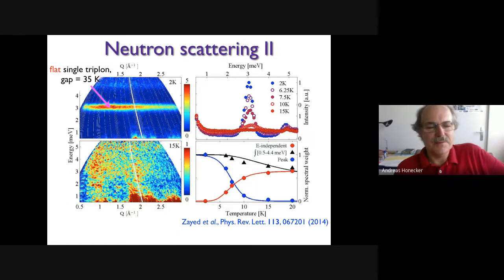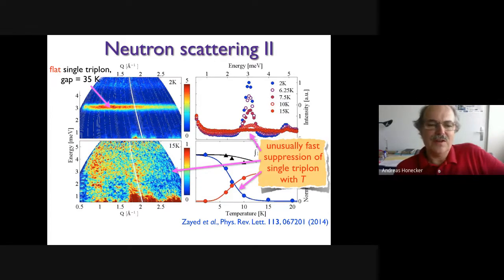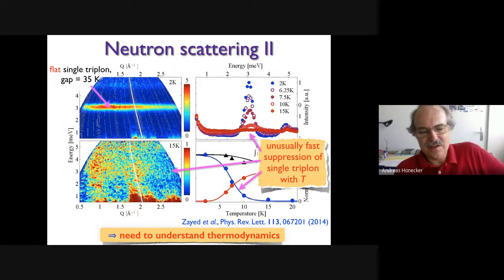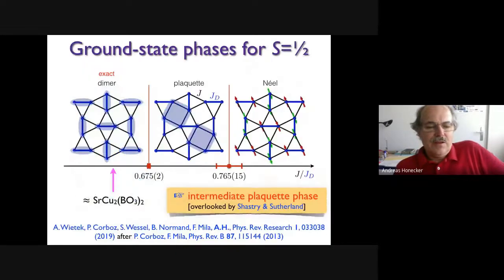Now, what is really striking in the rest of these plots is that if you go to a temperature of 15 Kelvin, which should be significantly below the 35 Kelvin, the dynamic response is completely changed. You see this in the scans, you see this in the intensity integrated plots here. Basically, the temperature scale where things are changing is 10 Kelvin, which is a factor 3 below what should be the intrinsic energy scale according to neutrons. And this is really extremely unusual and needs to be understood. And so that is basically a call for understanding thermodynamics. Okay.